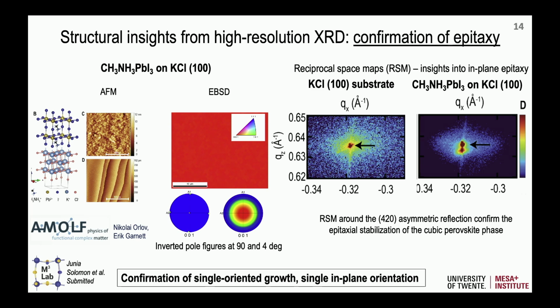Because polycrystalline films, we had different colors. But it was really amazing that we actually can prove with EBSD that we have a single-oriented film. So we have grains, but they are all single-oriented. And this confirmed, basically, is complementary with the reciprocal space maps. So it's a very exciting result, also an example of how collaborations can work when you have complementary characterization.